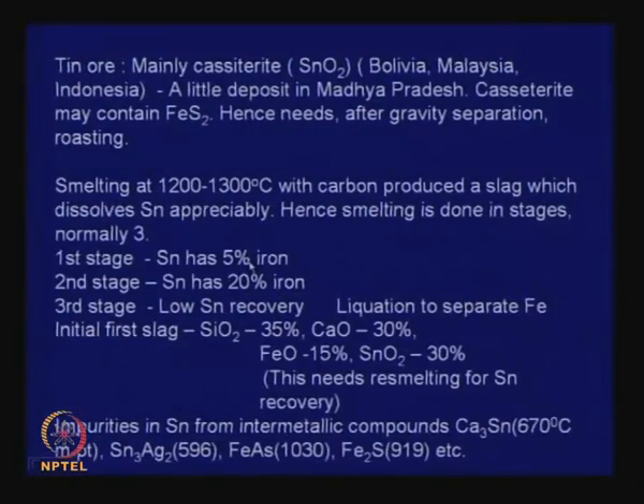But in that process, we have to let go a lot of tin oxide in the slag, does not matter. We will collect the slag and smelt it again with carbon to produce a tin which will now have more iron. In the third stage, again we will take the slag and smelt it, and there the tin recovery would be rather small.